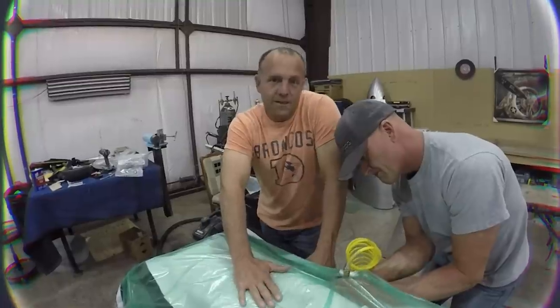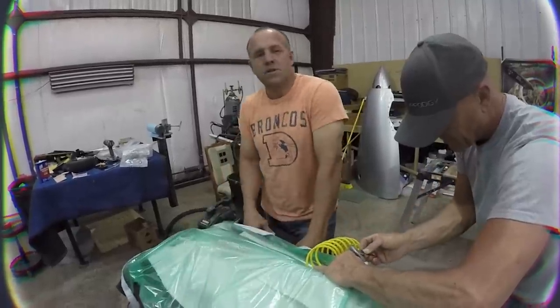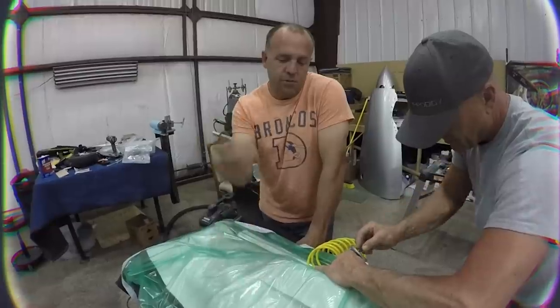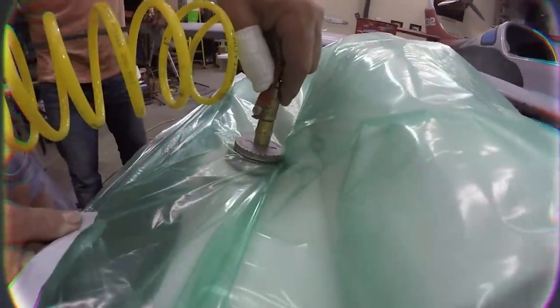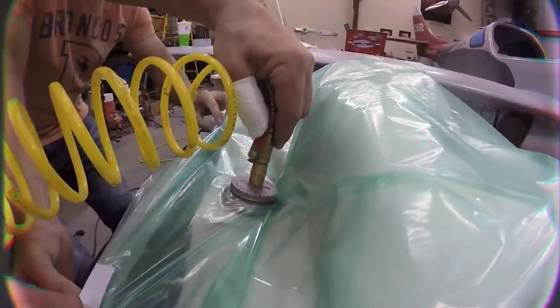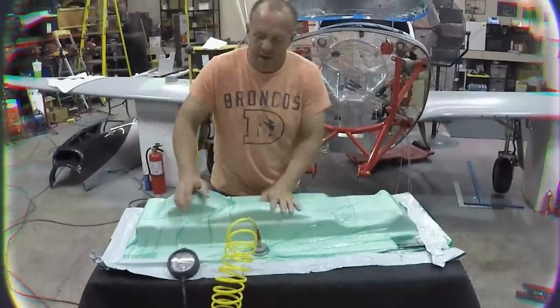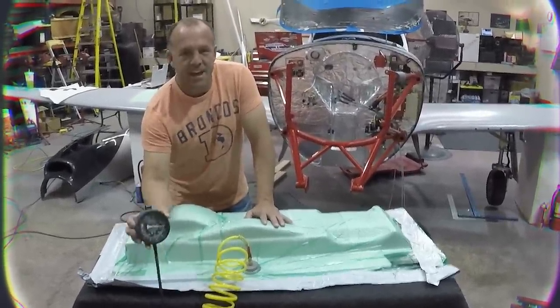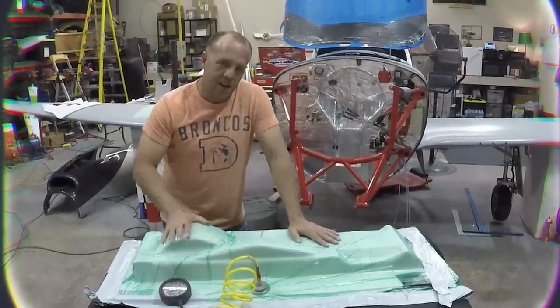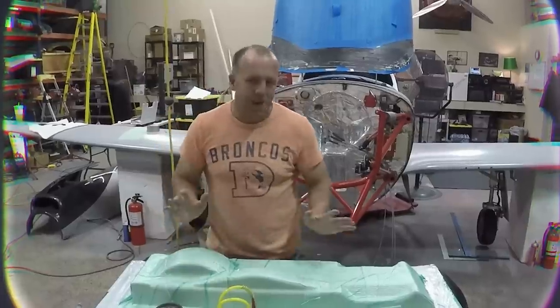We've got release film down, then we've got foam — this foam actually sucks the resin out. We're putting on a very stretchy film to bag it and suck all the air out. That puts so much pressure on the carbon fiber that the resin pulls up through into the feeder ply. Hopefully it pulls tight and we've got a good part. There was a little tiny leak — we found it and ended up with a ton of tape on here, but we're actually beyond the green, which means we're almost at negative 65. So we've got a good tight vacuum. You can see there's a little bit of wet color coming through the foam — that's a good sign, that means the resin is coming out of the carbon. We'll let this sit for the night and tomorrow we'll pull it apart, trim it up, sand it, and get it on the plate.